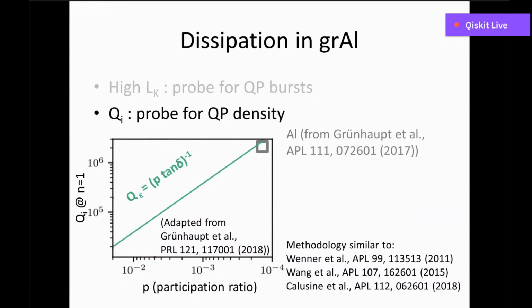Then can we do the same thing with granular aluminum? Can we decrease the participation ratio and get very high internal quality factors? When we start from a very big participation ratio, we do see an improvement when we reduce it, meaning that in that regime granular aluminum, as shown by this point, is dielectric limited, and decreasing the participation ratio puts the values on a slope, which interestingly shows a comparable tan delta to aluminum. But when we get to a regime where the participation ratio is very small, which would give us very good Qi as for aluminum, we find that granular aluminum resonators saturate on a floor and give us an order of magnitude smaller internal quality factor compared to similar geometry aluminum on the same substrate.